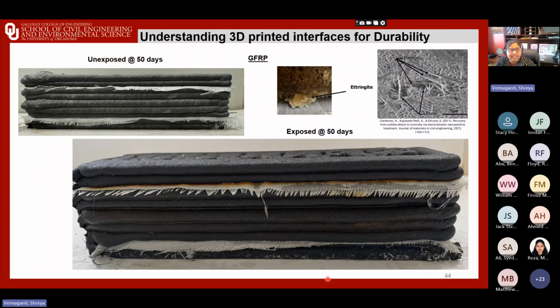Interestingly enough, if you look at the GFRP specimens that we put into the chemical ingress, the unexposed ones didn't show any discoloration. There were, however, on the chemical ingress specimens, some white deposits along the bottom interface. From our past studies where we've done some durability studies, we've seen ettringite being pushed out of the concrete itself because of the chemicals that are present in the chambers, especially sulfate and chloride rich. So these expansive ettringite can form and migrate towards voids and interfaces. And there is literature also to support that layered or cracked regions can act as preferential outlets for ettringite crystallization. So maybe they might be accessible pathways for moisture and ions. So we are trying to investigate more into that.